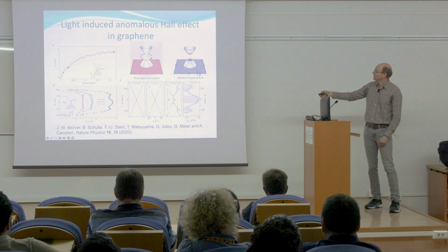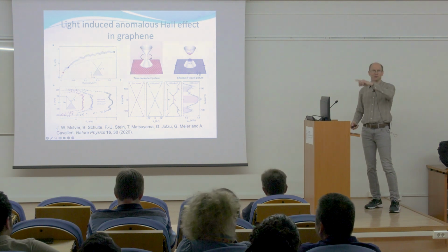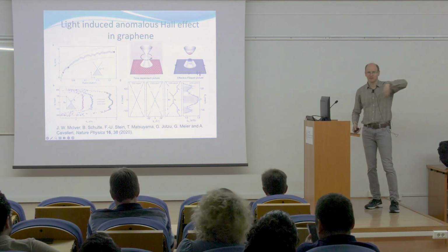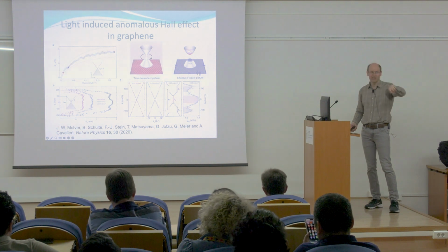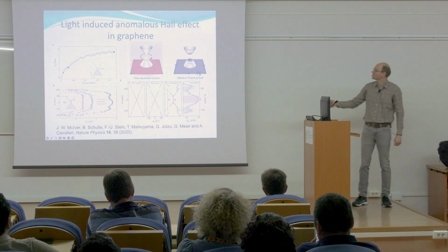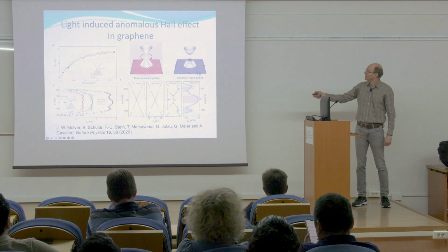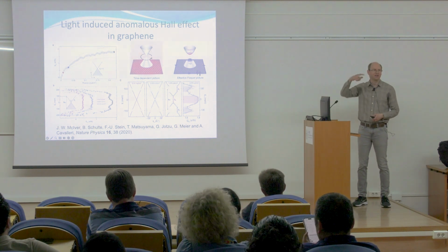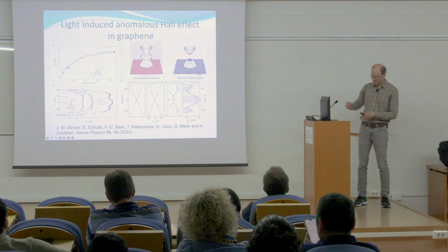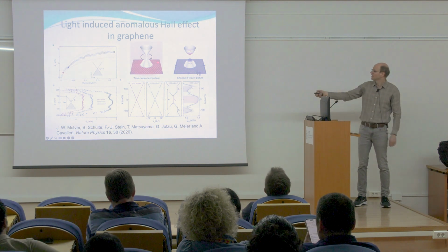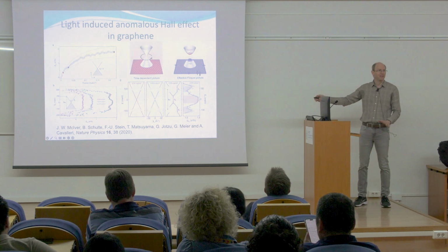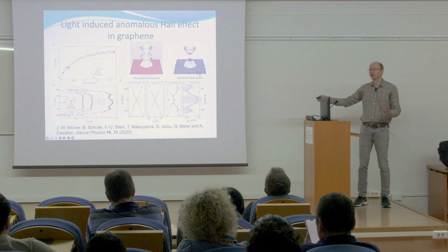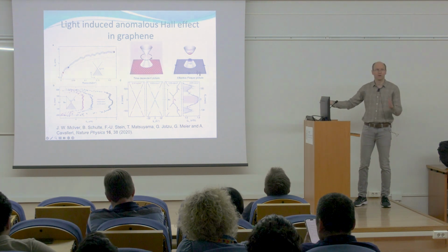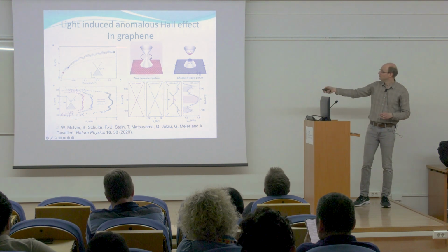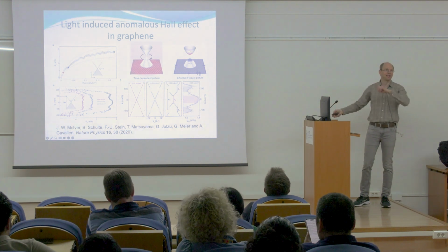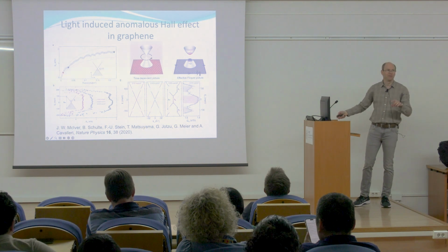If you shine light on it, which has a circular polarization, so that the electric field is winding around in a circle, say either a right-handed polarization or left-handed polarization, then that circulation in the electric field from the light changes the symmetries of the system in a fundamental way. So graphene by itself doesn't have any magnetic order, so it hasn't broken any time reversal symmetry. Magnetic order breaks time reversal symmetry. But if you impose a circularly polarized light on it, now you have broken time reversal symmetry.